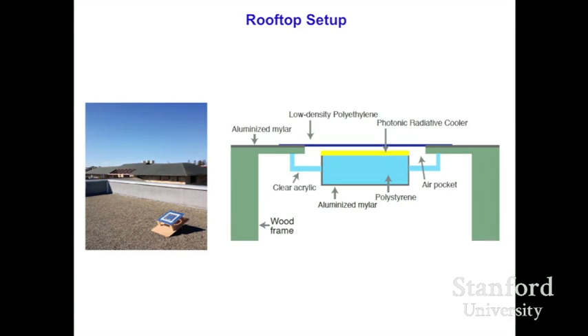And as a result, a lot of effort has been put into the thermal design in order to get this thing to work. Now, there are quite a few advances, and one of them is to design a transparent box around the sample so that nothing in direct contact with the sample actually gets heated up by the sun. And we use low-density polyethylene to cover the opening of the sample, and that provides radiative access. It's very transparent to infrared light, but in the meantime, it cuts down convection. And low-density polyethylene turned out to be basically kitchen plastic wrap, so we have quite a few of those.